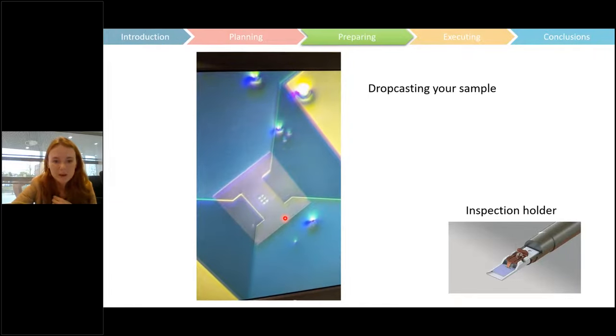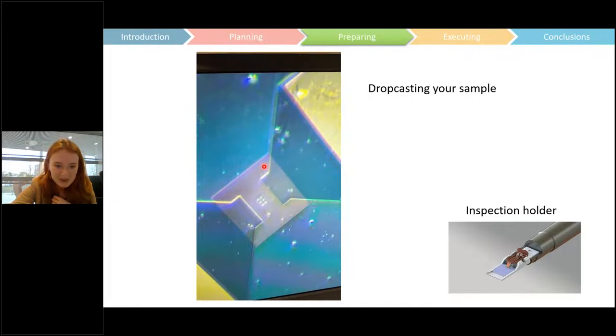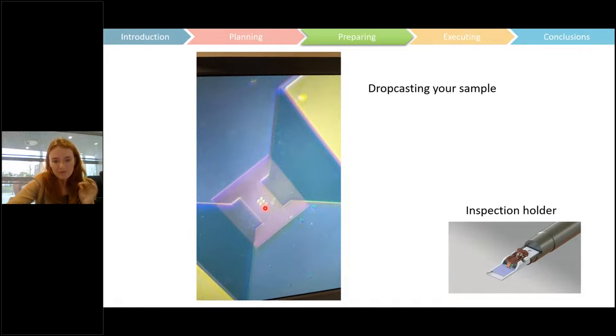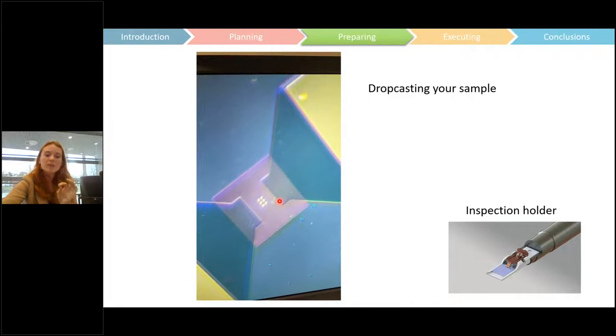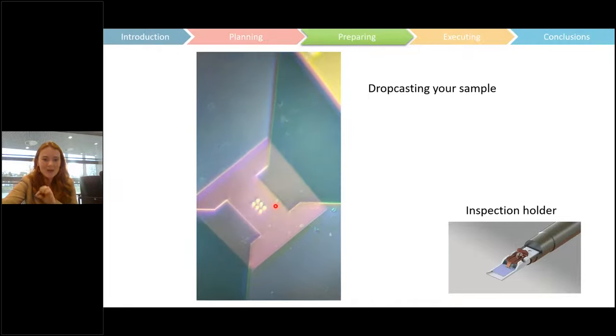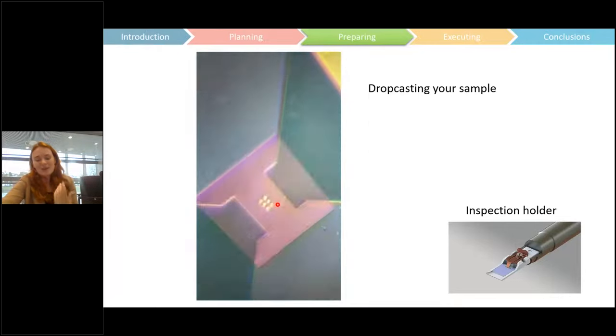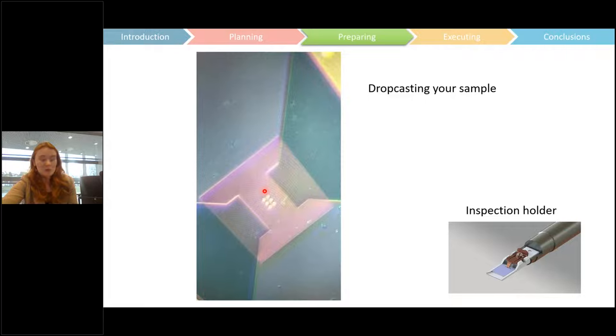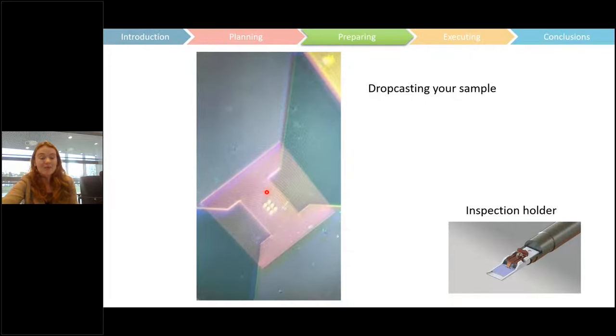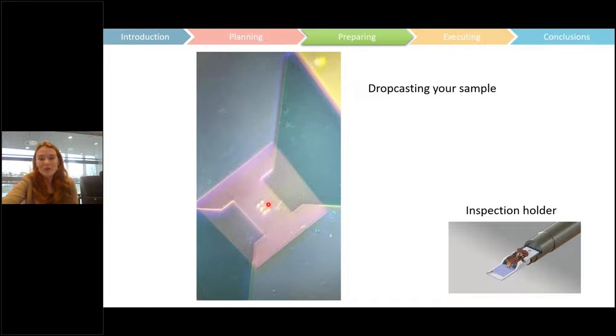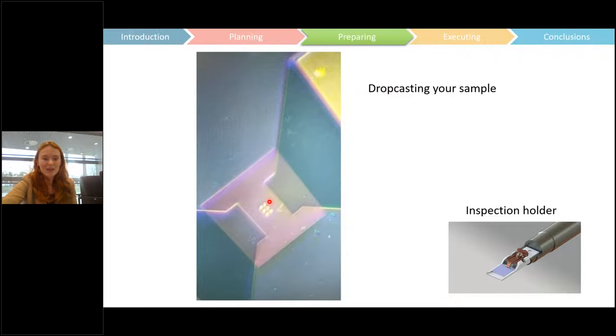You can see it now with the bigger particles, there's this surface tension. But as it dries, if you watch really carefully, you can capture the moment at which it dries, and you can see whether it has landed on your six windows or not. If you don't have an inspection holder, but you do have an optical microscope lying around, this is a really easy way to know whether you've got the sample in the place that you want it. You should do it again in a second in this video, so you can capture it again.